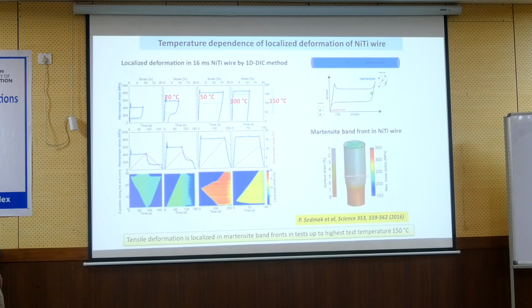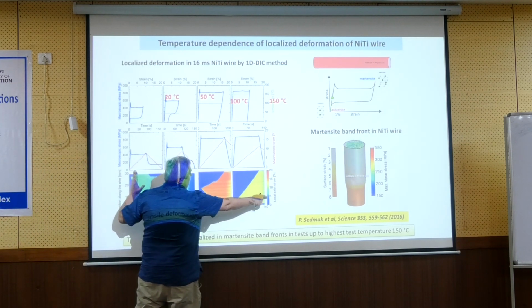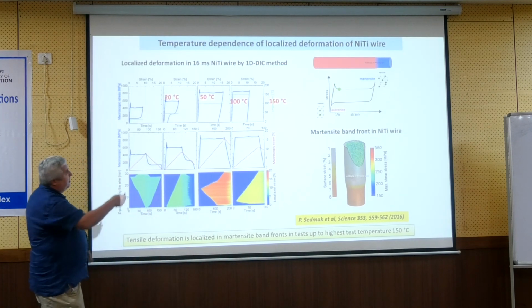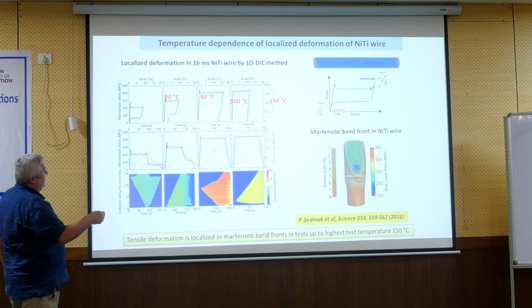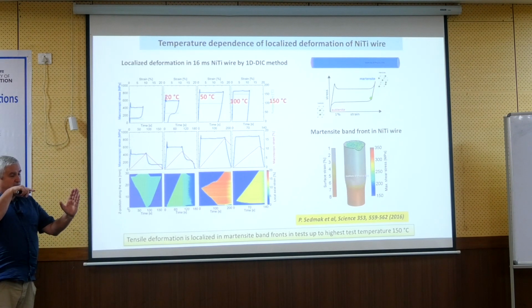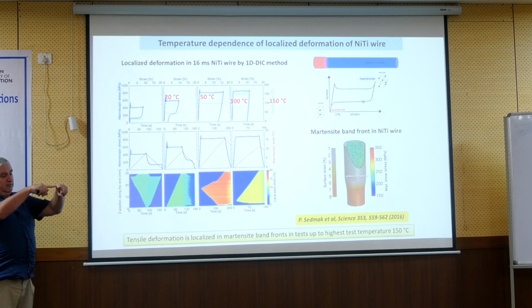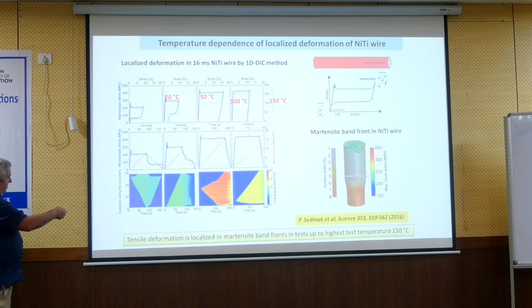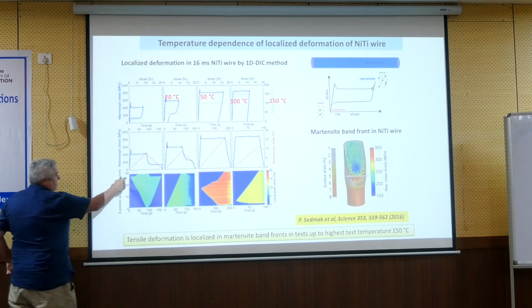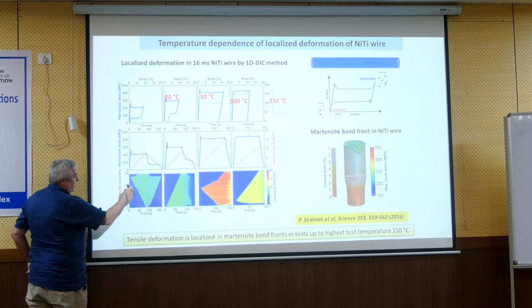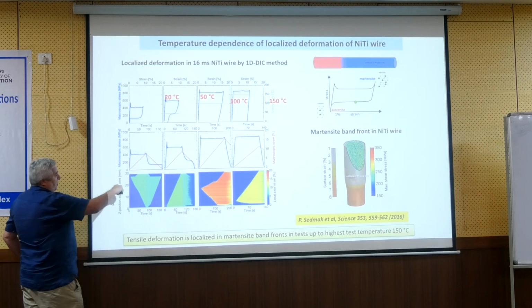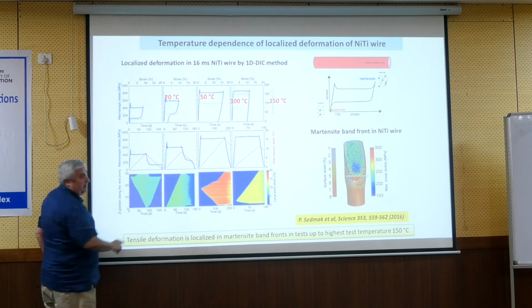Not really. I will use these figures a lot. If the deformation is homogeneous, there will be a gradual change, like from blue to red over here. But because the deformation is localized, with this method we observe the wire with a camera, and from the change of the pattern on the surface we evaluate the strains. So we have something like an extensometer which evaluates the strains at many points along the length of the wire. Strains are the color here, and this is the motion of the interface during forward transformation, and this is the motion during the reverse transformation.